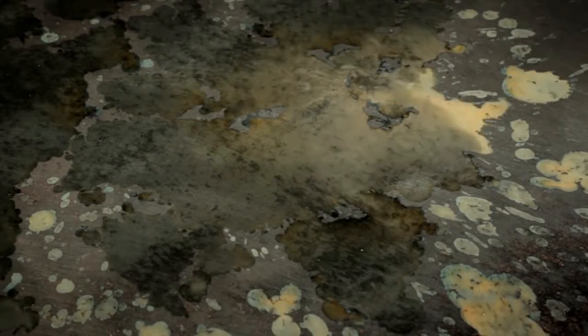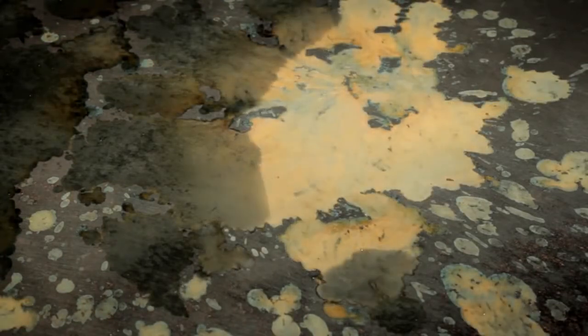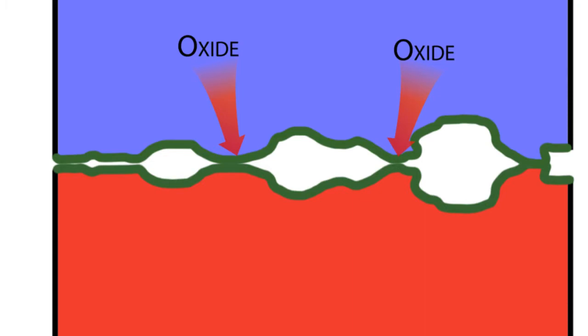Same thing happens with aluminum, but in the case of iron, the rust keeps falling off and eventually the part will rust to nothing. Aluminum has a benefit in that it reacts with the oxygen and creates a protective coating that limits the oxidation from eating the aluminum. The problem is that layer is an insulating layer. So if that layer is not removed prior to making a connection, you actually have an insulative layer inside your connector. So it's important that when you're making your connection, you remove that oxidation layer prior to installation.